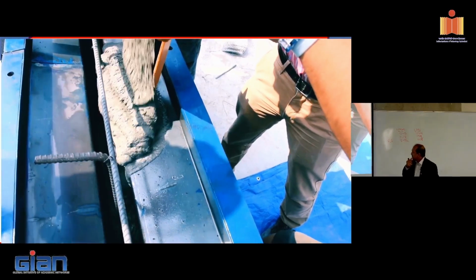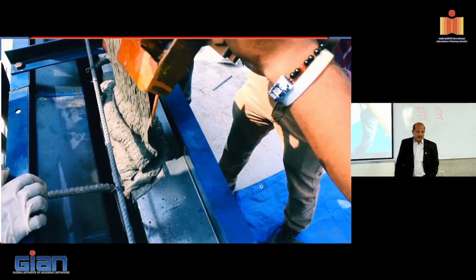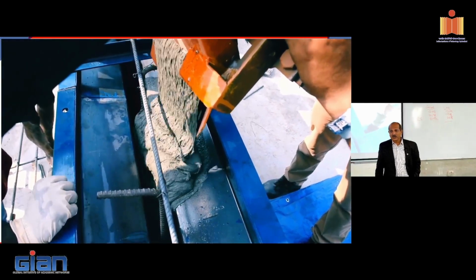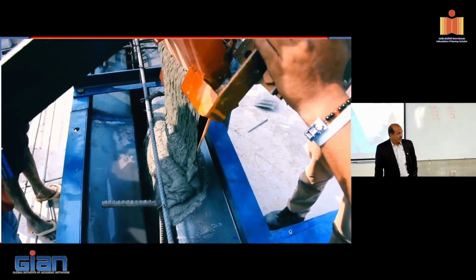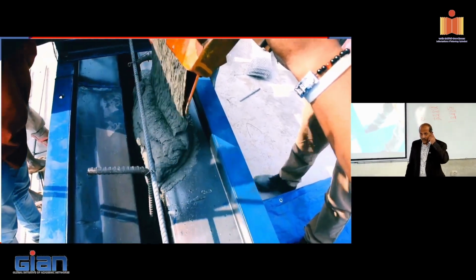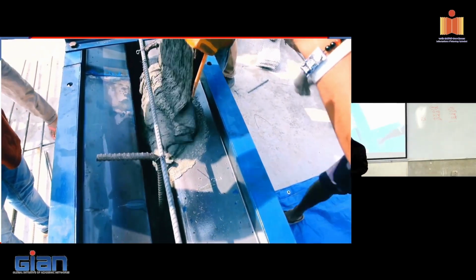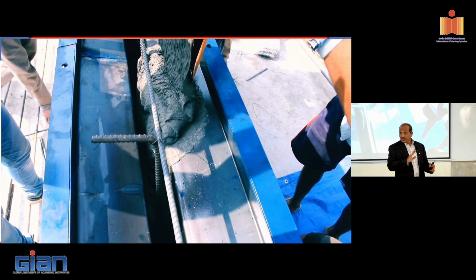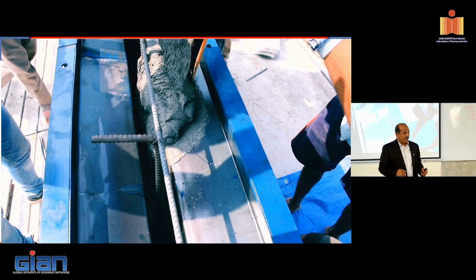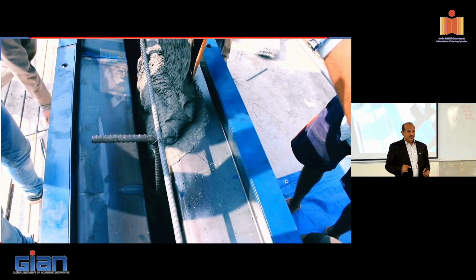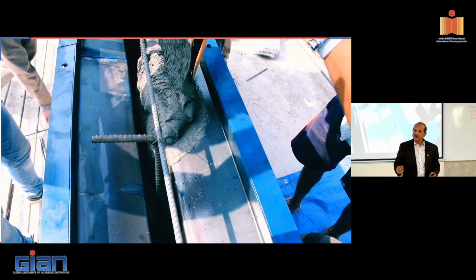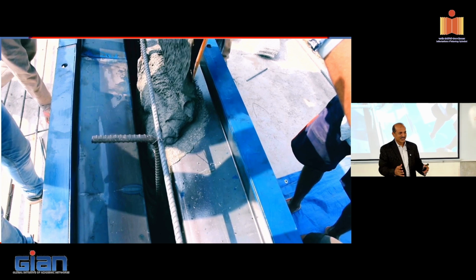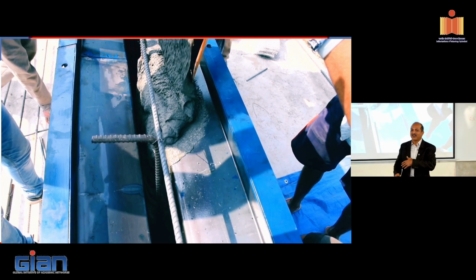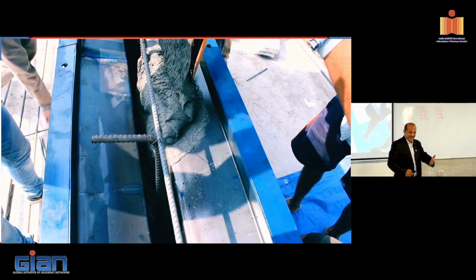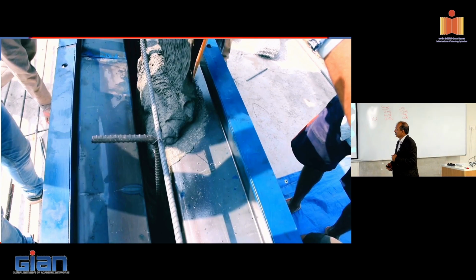And you can see that material is flowing. What were the challenges? We were working in a 40 degrees temperature environment outside. That was the biggest challenge. The first time we mixed UHPC outside, we immediately figured out that we need to take control. Although we were mixing ice and everything, it was fully iced, but we learned a trick immediately that before we start the mixer, we should cool down the mixer by putting ice in it, just ice. Okay, and you run it for 5-10 minutes with quite a bit of ice, cool down the mixer in that environment, and then start mixing UHPC. It is going to have a very positive effect. So that is something we learned from the site, doing the first project in a 40 degrees centigrade environment.